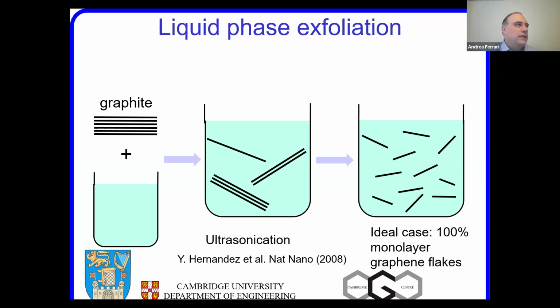It was Yenny Hernandez, the student at the time, now a professor, that did this work, published in 2008. Quite interesting, the title of the publication is High Yield Production of Graphene by Liquid Phase Exfoliation. But if you read carefully the abstract, the yield was not 100%, but 0.8%. It still claimed to be a high yield because before the yield was 0, so 0.8 is much bigger than 0, especially if you do the ratio.